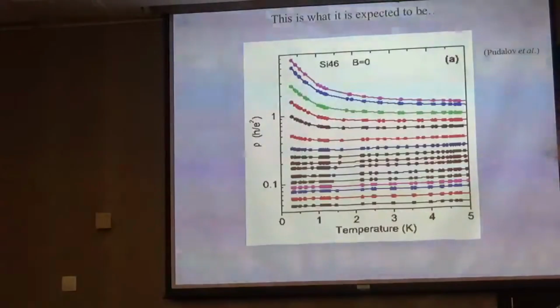So that's what it is expected to be according to the conventional theory. I plot here the log of resistance in units of h over e squared. It's about 25 kilo ohm. I'm not going to go into details why we measure in those units. It's the quantum of resistance. And I plotted it as a function of temperature in kelvins. As we approach zero, those different curves correspond to different numbers of electrons. So here we have a lot of electrons, here we have very few electrons.